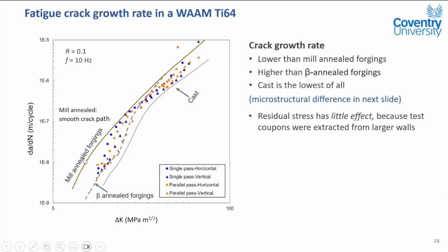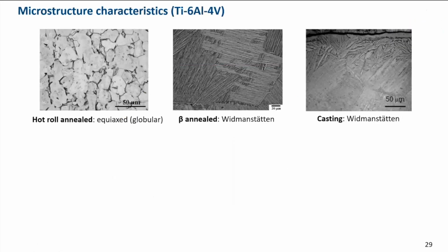So the mill annealed forgings has the fastest growth rate, and the casting has the lowest one. And if we do a beta annealing for the mill annealed, the crack growth rate slows down. So I will show the next slides. These all rely on the microstructure difference. The traditional hot rolled material has an equiaxed or globular microstructure. They don't stop crack growth. Crack can just go around them, around the grains.